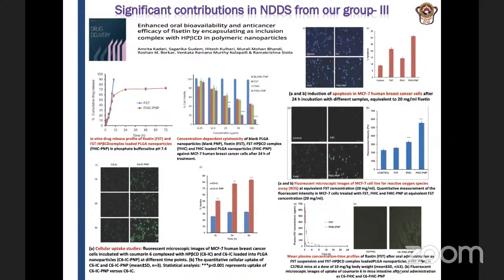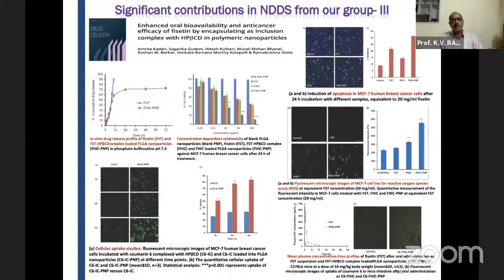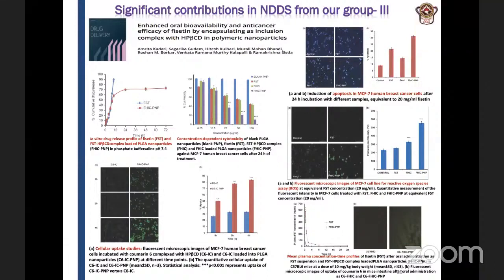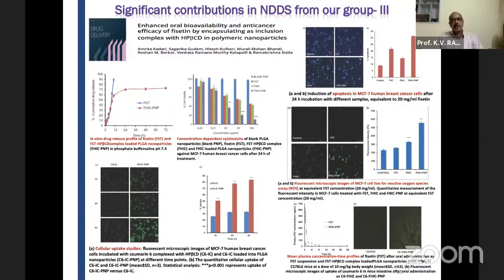By preparing the HP-beta-CD complex of fisetin, we improved the solubility of the drug from approximately 5 to 860 micrograms per ml. Using this drug complex, we prepared polymeric nanoparticles and evaluated them for various characteristics like drug release, cytotoxicity studies, cellular uptake studies, and other studies. We have even done in vivo studies in mice. The results clearly confirmed the applicability of fisetin through the oral route, wherein there were no earlier reports of its oral administration, and we were successful. We improved the bioavailability of this fisetin when administered orally by about 13 times, and the Cmax by about 8.5 times, which is a significant contribution.